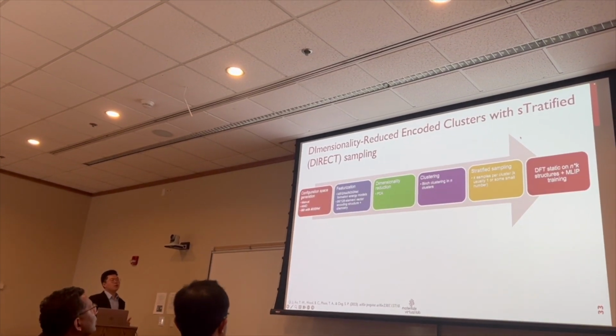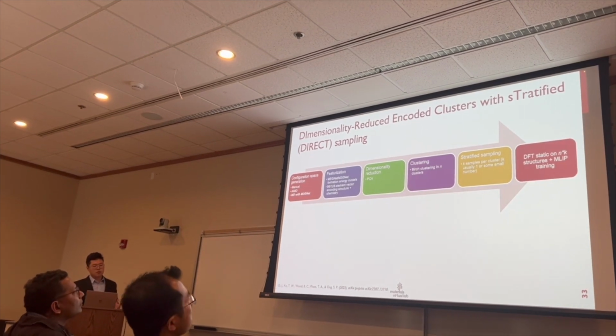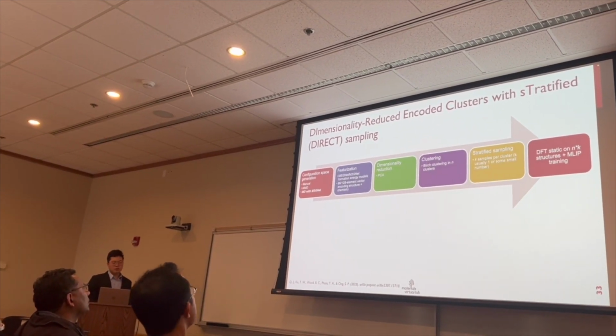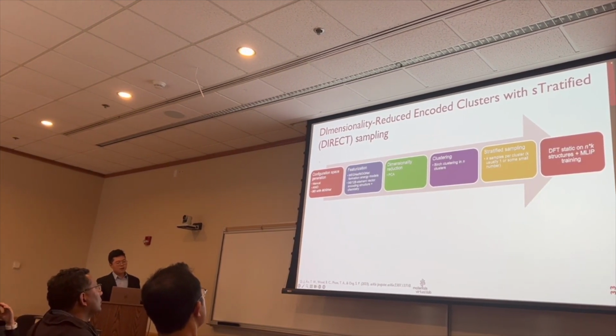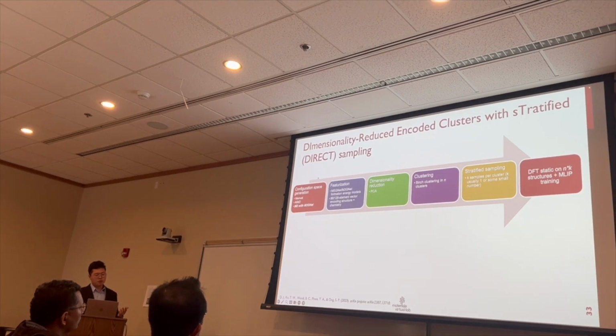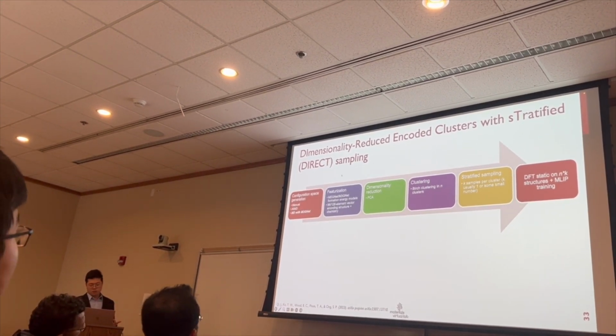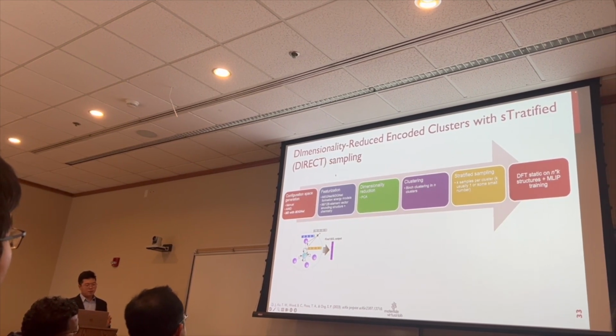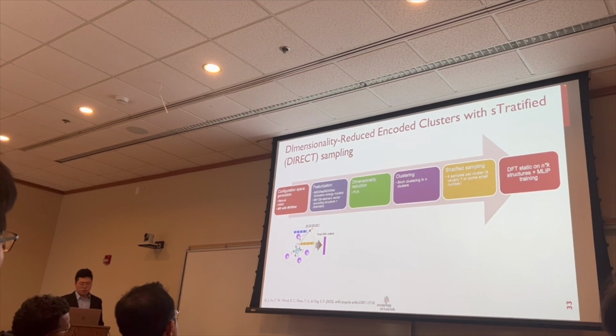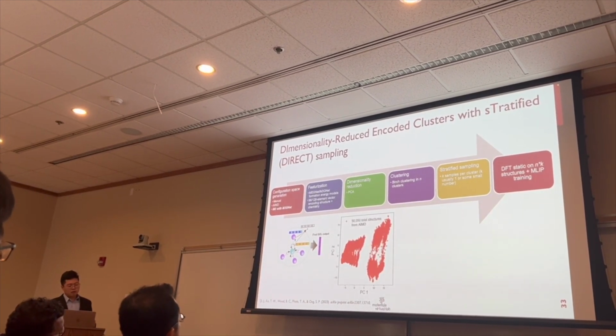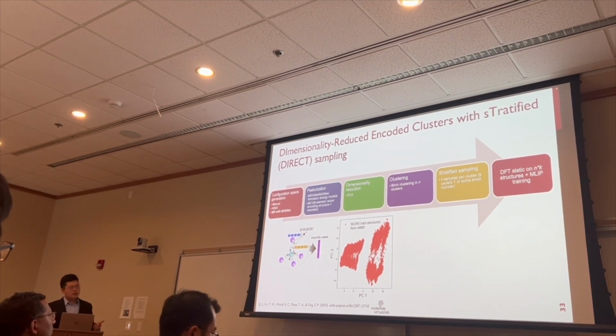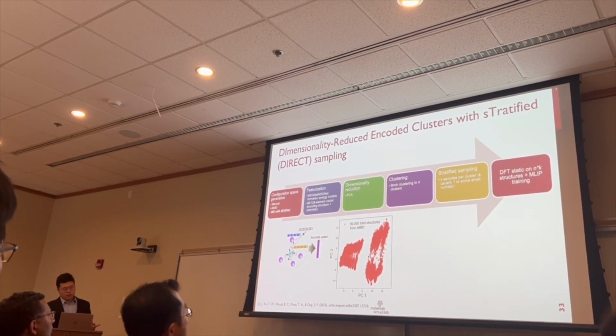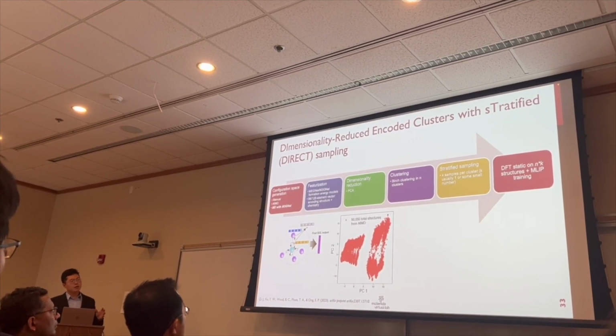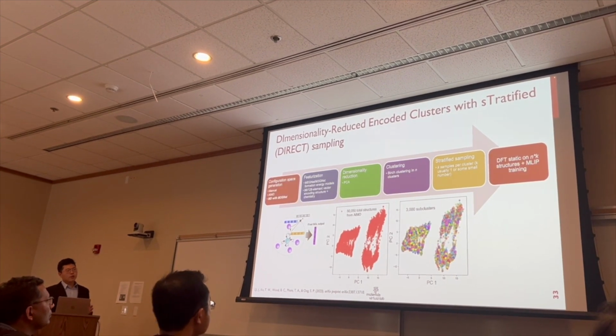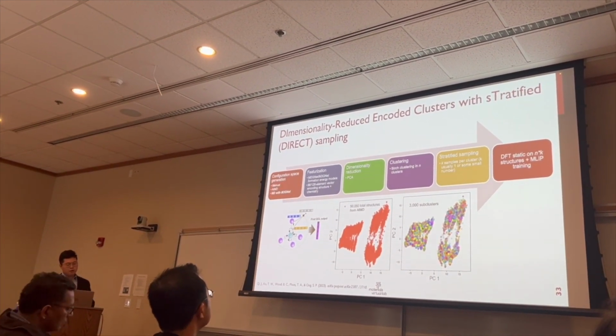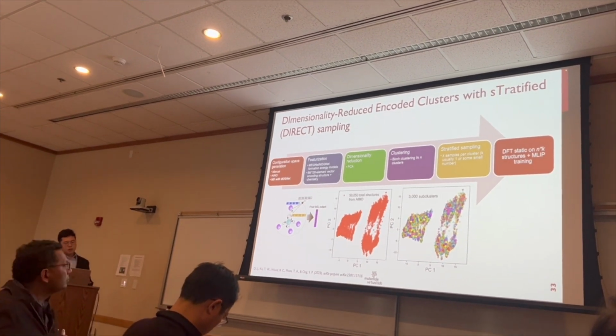And that's how we invented this dimensionality-reduced encoded clusters with stratified sampling method. In this sampling method, given a configuration space, for example, here, the Materials Project dataset, we can use the M3GNet model to do the featurization to process the structures into features. And then we do a dimensionality reduction with PCA to get the reduced feature space. And the next crucial step is that we do a clustering for those structures according to their location in the feature space.